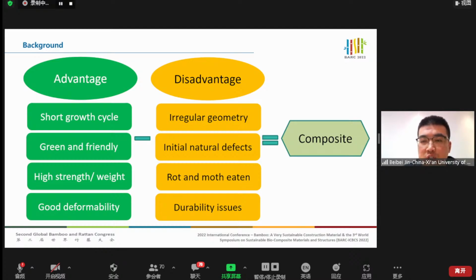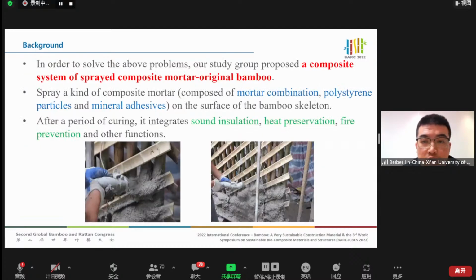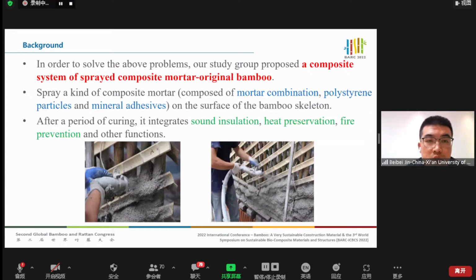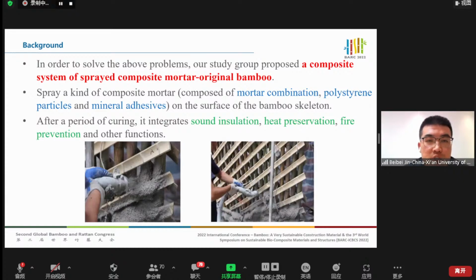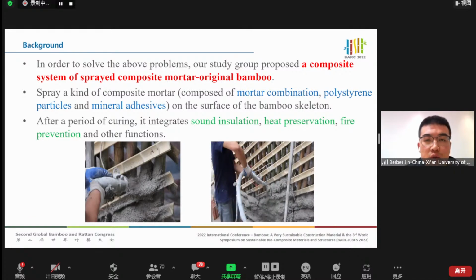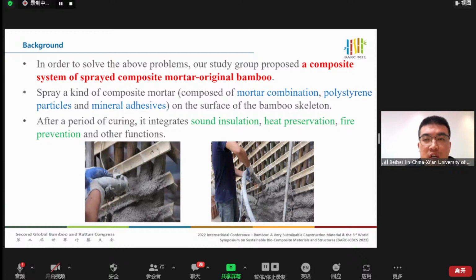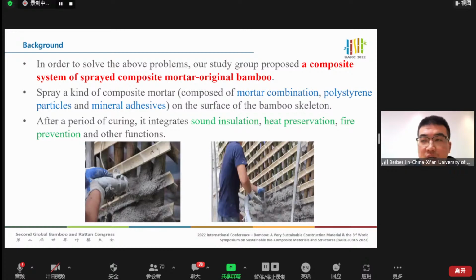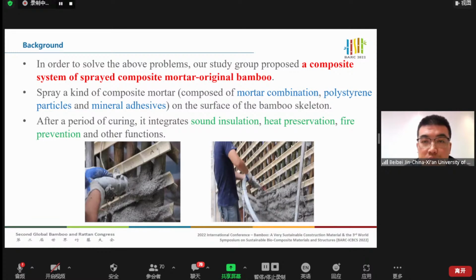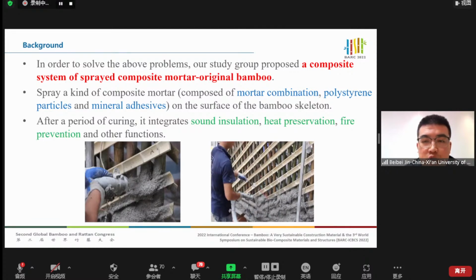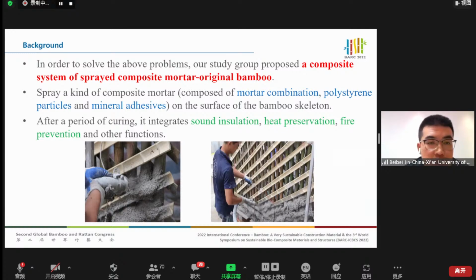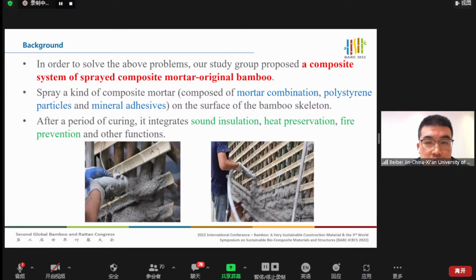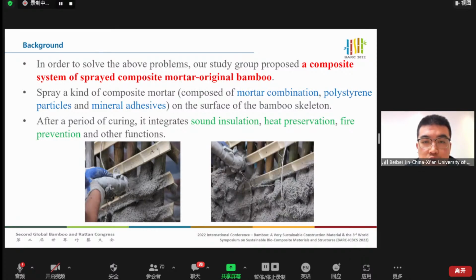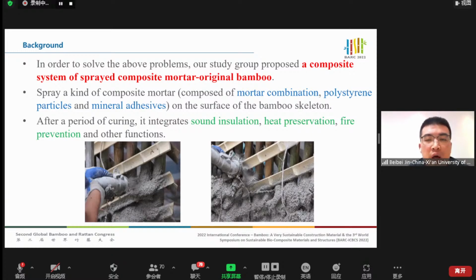So when we combine the two sides, we try to use a composite design. In our team, we propose a new type of bamboo structure, sprayed composite mortar and round bamboo. And we published some papers in Chinese and foreign journals. We spray a kind of composite mortar composed of mortar combination, polystyrene particles, and mineral adhesives on the surface of bamboo skeleton. And after a period of curing, it integrates sound insulation, heat preservation, and fire retardation, and other structural functions.